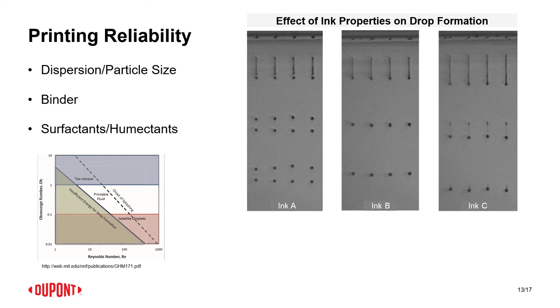What this chart really shows with these different inks is you can have a situation where you eject a drop, you form a tail, and the tail breaks off and the 2 drops never catch up, right? So that's going to have a negative impact on your image quality. You can form an ideal drop right off the bat, or you can form a tail that almost gives you a satellite, but it actually is able to catch up with the drop before it hits the surface. The point here is that how this behaves can really be tuned by your dispersion or particle size, but also even by the polymers that you're using. So you could have something that breaks up into a less than ideal drop, but because of the components that are in the ink, they're able to catch up and form an ideal drop before hitting the substrate.